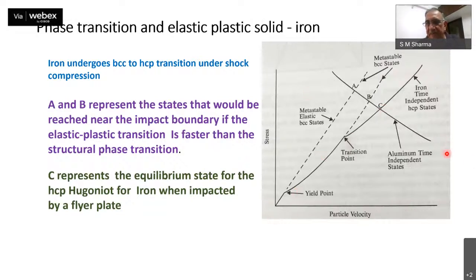So let us say iron was impacting an aluminum plate. Incidentally, aluminum other than HEL doesn't show any other phase transformations. So suppose one is doing that experiment, either aluminum or let us say sapphire, it makes an impact. Then you expect that it should represent a metastable state where it intersects the elastic Hugoniot of the target with the impacting material, and then another metastable state, which is essentially an extension of this plastically deformed state, and then finally the one after the transition. So you expect that if iron makes an impact and you study the shock wave propagation, you're likely to see three waves.